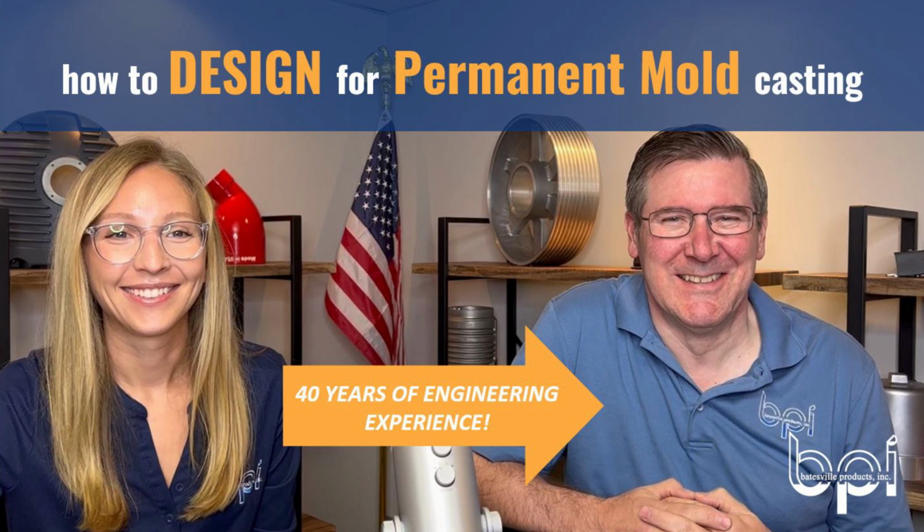And of course, we use the draft to get the part out of the mold. You want the draft to move away from the parting line so that the parts release accurately off the mold. And this is typical of a permanent mold casting where the parts will stay with the top mold, the cope, and they'll be ejected by pins from that cope, onto, in this case, a plate that we move into place to catch the castings. And the proper draft permits the mold to last as long as possible.